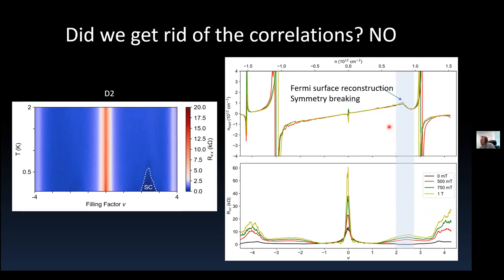So at least what this tells me is that even at low angles, you can still have some sort of correlation effects. They are shifted. We are significantly shifted from the nu equals 2, and maybe this actually highlights that there might be some Van Hove singularity physics going on, where things at low angles can move around.